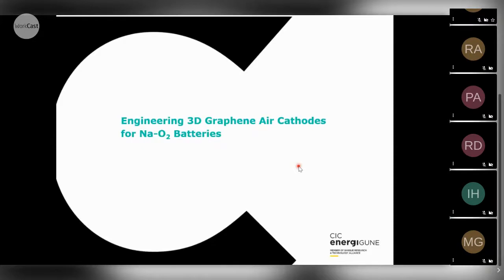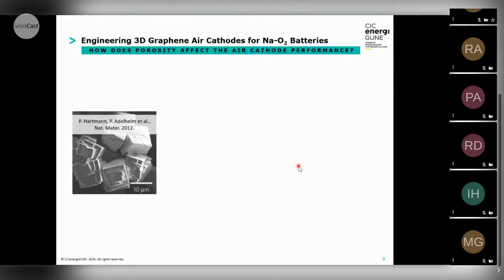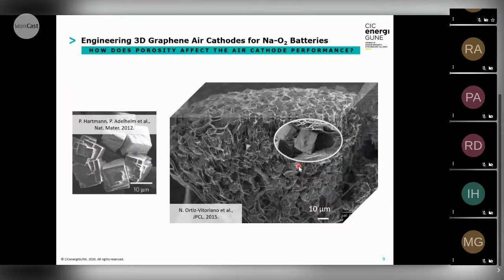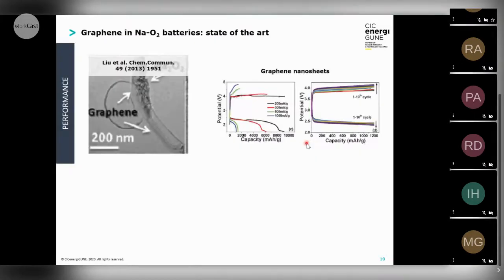So the first part, in the case of the graphene, we already know that the cathode morphology is really important. It's not the same to have these carbon fibers where these cubes accommodate on the surface, or to have a really high surface area cathode. This is the case of carbon nanotubes, where you can accommodate the discharge products all over the surface. So for that, we wanted to engineer 3D graphene air cathodes.